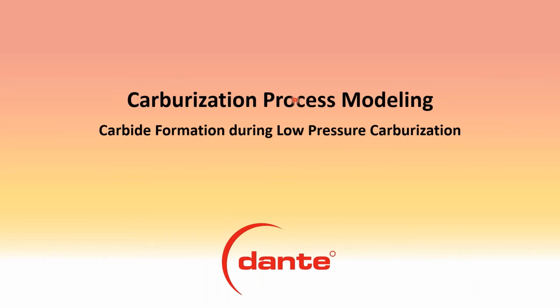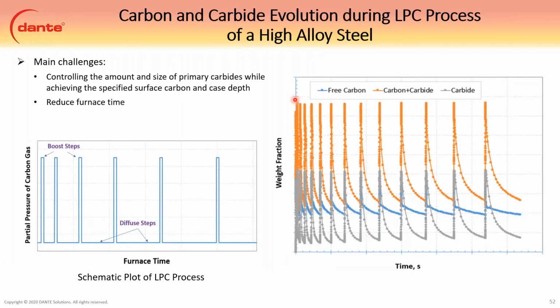Carbide formation. This is huge, especially for high alloy steels. You cannot model low pressure carburization of high alloy and some medium alloy steels without considering carbide formation. Why is this? Because as you pump in carbon, you saturate the austenite, and then you start to form carbides. Those carbides grow. So our plot on the right shows, the blue lines down here are carbon in austenite. The gray line is the carbon that is in carbide form, and the orange line is a combination of the two. So you can see we build a carbide up. That carbide then dissolves during the diffuse stage.